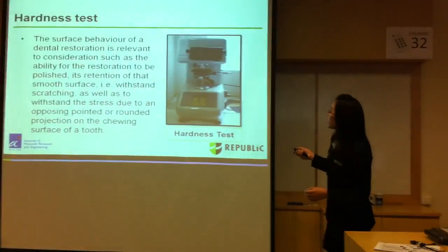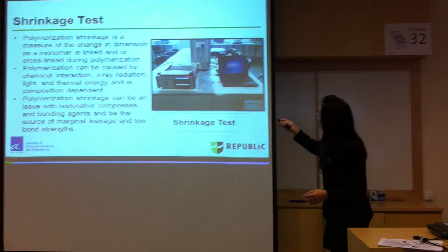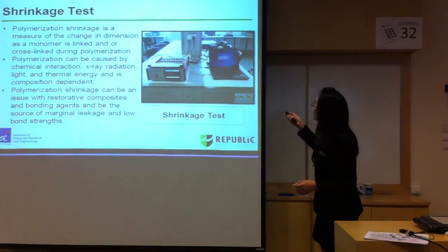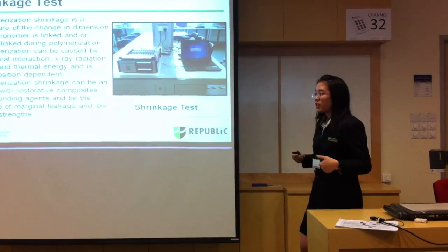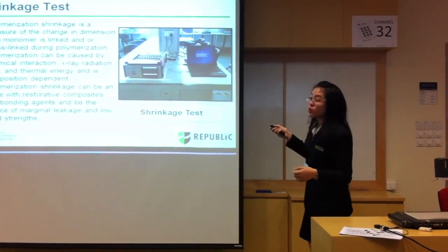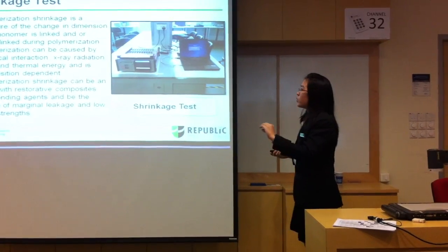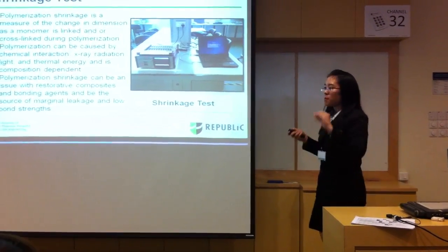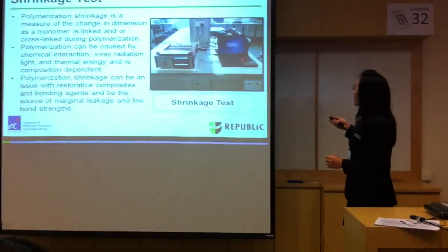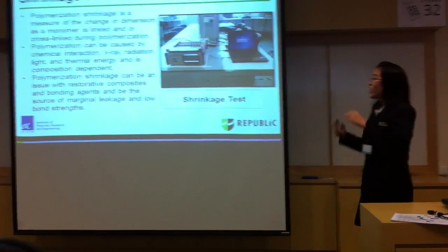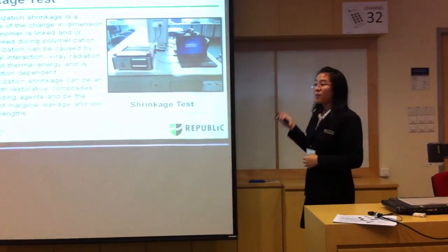Yes. How do you measure the shrinkage of that material? We make use of the data logger machine, and this data logger machine is connected to this laptop, and this laptop has a computational Excel sheet. We connect the material to a strain gauge and the strain gauge to this data logger, and then it will beep every second. Every second it beeps, it will record the data into this computer, and then we will retrieve the results from this computer.